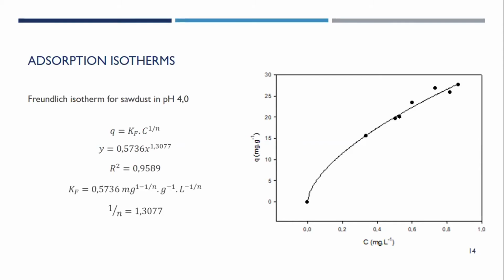For sawdust, the Freundlich equation at a pH value of 4 shows the Freundlich constant to be 0.5736 and the exponent 1 over n to be 1.3077. Once again, the exponent did not show significant change, and while the Freundlich constant did increase with the decrease of pH, it still pales in comparison to the values shown by Chitosan in the same conditions.